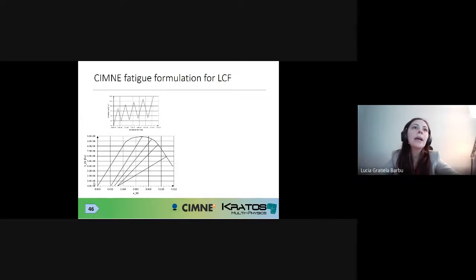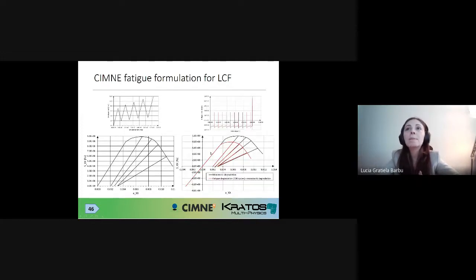And here, for instance, you can see an interesting case when you apply this type of loading and you begin with a completely plastic behavior, then you pass into a transition zone where you have plasticity accumulated with damage, and you continue up to a point where you begin to exhibit exclusively damage, okay? This is perfectly possible with this model. And another combination where we have cyclic loading, 10,000 cycles applied, and after that we break the sample monotonically. During these cycles, we do this unloading here, where you can see how the behavior changes from plasticity, to plasticity with damage, and in the end, we only exhibit a damage behavior in the part where softening is obviously exhibited.